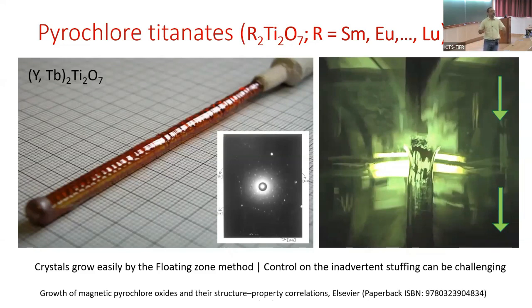So you cast it in the form of a rod. And you bring the seed crystal and you get this melt over here. And then you have to start pulling this crystal down. At the same time, in order to feed the zone, this is the molten zone, you have to move your material down at the same rate. And if you do it carefully, you get very nice crystals, like the one which is shown over here.